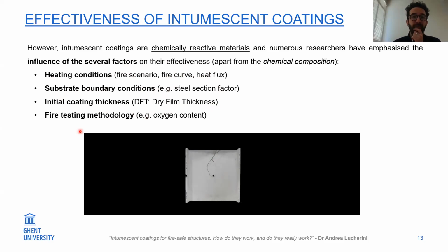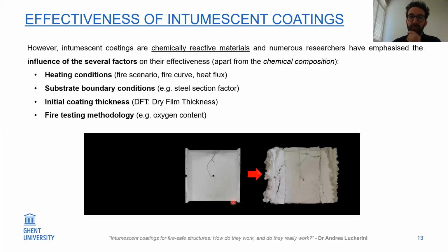And this is an example that I showed you earlier. This is the same I-beam. This is from my master thesis at the Technical University of Denmark. What you can see here is an I-beam that is protected with intumescent coating. And when it's exposed to a fast-growing fire, like for example the standard fire resistance curve, you can see that the coating swells and creates a very thick and dense char that protects the steel beam from the fire.